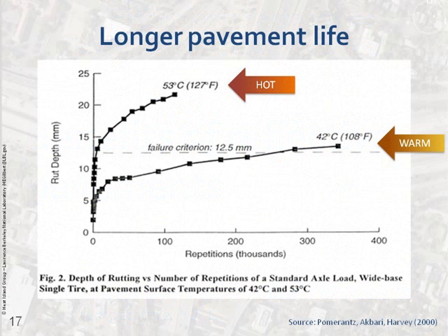So here you see two different pavement systems compared, and on the top, there's a hot surface that absorbs more sunlight and therefore ruts or degrades much more quickly, with fewer repetitions to get to the failure criterion rut depth. The surface that only ever gets warm rather than hot is able to endure many more repetitions before it is determined to be failed.